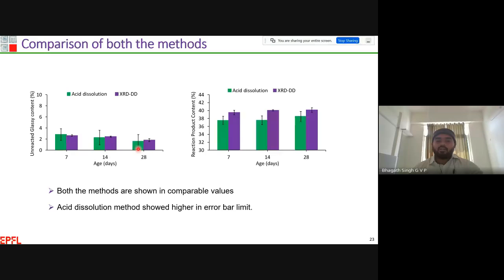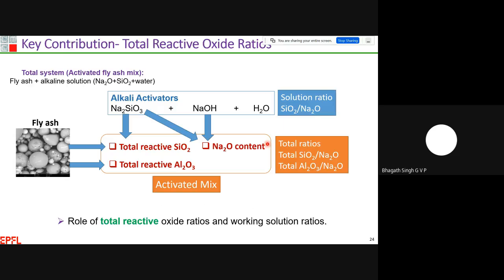And this higher error bar is due to, as I said earlier, some of the particles being very sensitive to the acid dissolution, and also some of the sample may slip through during the wet chemistry analysis. Due to these reasons, we can't predict exactly what happens in the acid dissolution technique. Thereby, the XRD technique is a completely controlled process, and we can see the error bar is also very small compared to the acid dissolution technique.